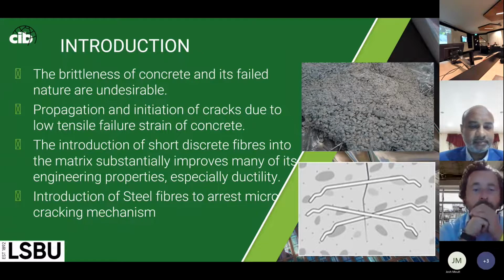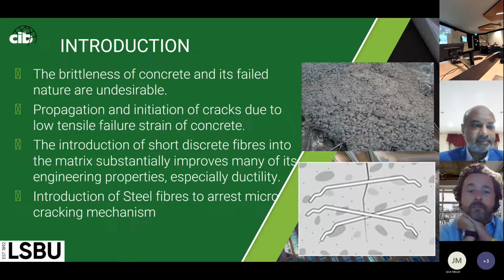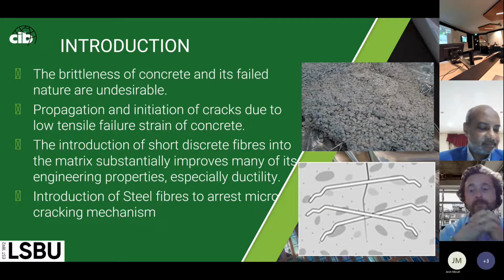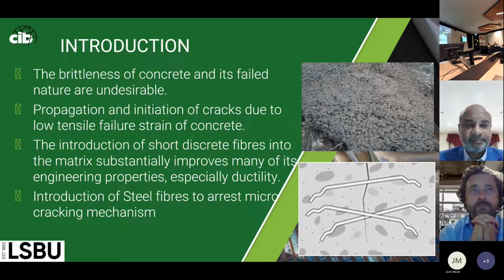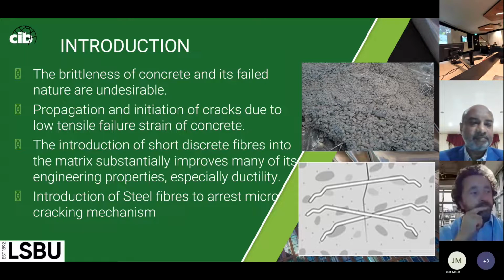The conventional reinforcement bars are stationary within the region of the concrete. When a crack is initiated, ideally there should be transfer of load from the concrete to the reinforcement bar. But before this load is fully transferred, initiation of the crack has occurred. We need something that will provide multi-dimensional resistance to the crack. That's what steel fibers do within the concrete: they stop, resist, and bridge the initiation and propagation of cracks from micro to macro.